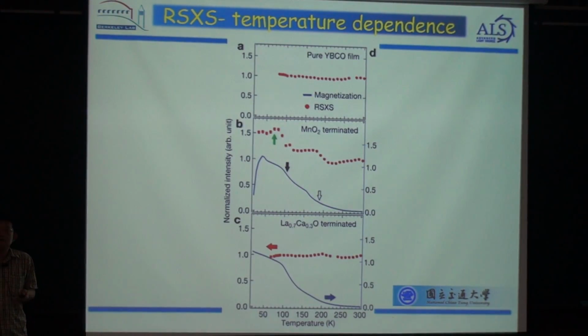Okay. So when this kind of order happens, there are several transitions that could happen in materials. One is the structural phase transition, but from this contrast experiment we already know that there's no structural phase transition of the pure YBCO throughout the whole temperature region. So this is definitely not a structural phase transition. But what can it be?